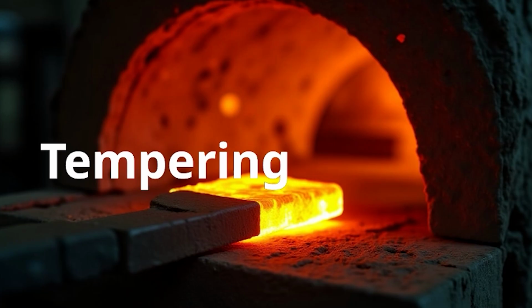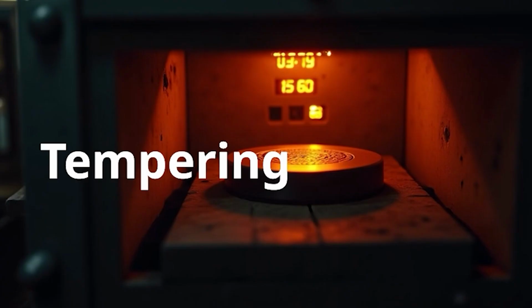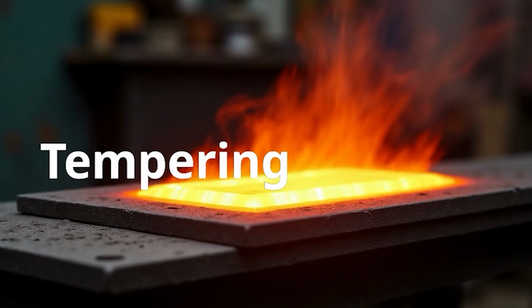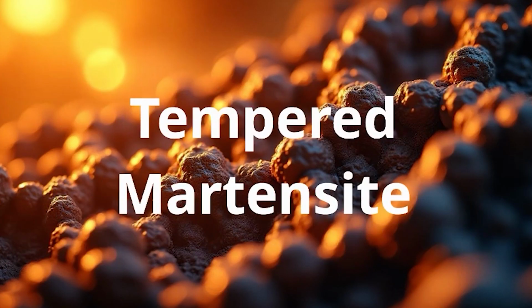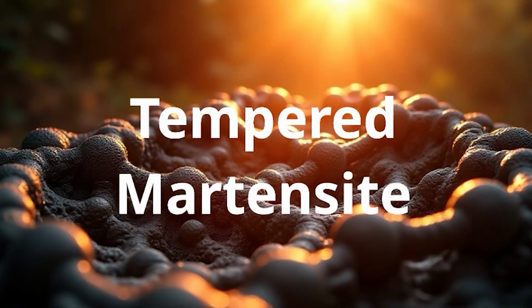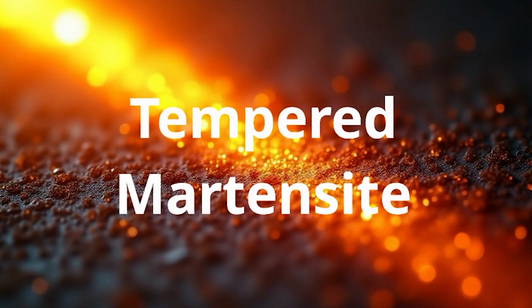The quenched martensite steel is reheated to temperatures between 200 to 600 degrees Celsius, below the levels needed for austenite transformation. It's held at this constant temperature for a defined period, anywhere from a few minutes to several hours, before air cooling. During tempering, excess carbon atoms trapped in the distorted martensite lattice diffuse out and combine to form extremely fine particles of cementite. This allows the lattice to relax back towards a body-centered cubic ferrite structure.